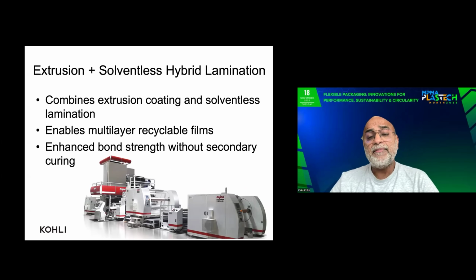Extrusion and solventless hybrid lamination—in India, the snack food industry is moving towards a 4-layer structure. So the first 3 layers are laminated using an extrusion laminator, and the sealant layer uses a solventless laminator. This is very big in India, especially for chips from Lay's, from PepsiCo. It combines extrusion coating and solventless lamination application, enabling you to produce a multi-layer recyclable film and enhancing bond strength without any secondary curing time. So your productivity can increase because there is no curing required when using an extrusion laminator.